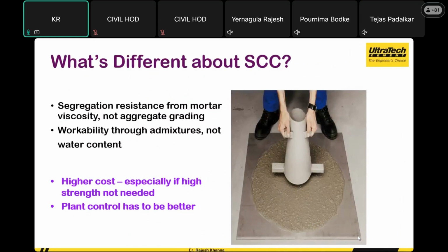The cost may be initially high, but now with the current developments that we have in the admixtures, as I said, like viscosity modifying agents, which are combinedly given in the admixture itself, it will help you get a more economical mix. In olden days, maybe in our colleges and in our laboratories also we have the slump cone, and when the slump is beyond 200, we say this is a collapsed concrete. But when we are talking about self-compacting concrete, we don't talk slump, we only talk flow. The flow of this concrete is about 500 to 600 mm. So it has to be tested on a flow table. It should have a high control for its flowing and filling abilities.